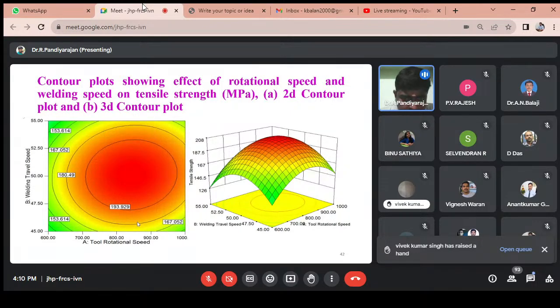For example, the left side shows the 2D contour plot and the right side shows the 3D contour plot. The x-axis shows the tool rotational speed and the y-axis shows the welding travel speed. On the x-axis we take a range of 600 to 1000 as minimum and maximum. On the y-axis, the welding travel speed minimum is 45 to 50. A tool rotational speed of 850 to 900 and a travel speed of 50 to 55 produce the maximum tensile strength.